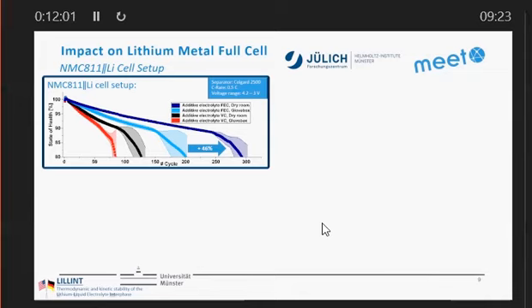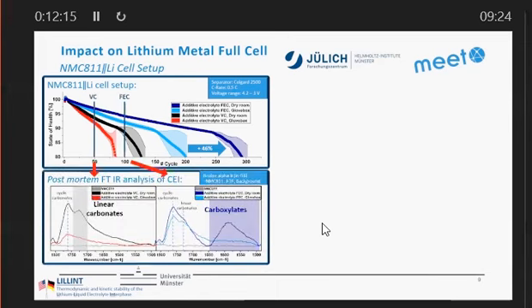This indicated to us, especially because of the VC thing, that something might happen at the cathode too, not only at the anode, because it's very clear that at the anode, because of the activity of lithium metal, something happens, and this is not very spectacular. It has been observed in literature. If you look at the CEI, the cathode electrolyte interface, you see that in the case of VC, we see linear carbonates, which differ in amount between glove box and dry room. But especially for the FEC, we see carboxylates, which we do not see in the glove box, which we only see in the dry room.